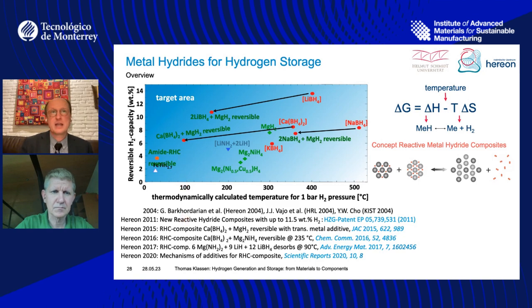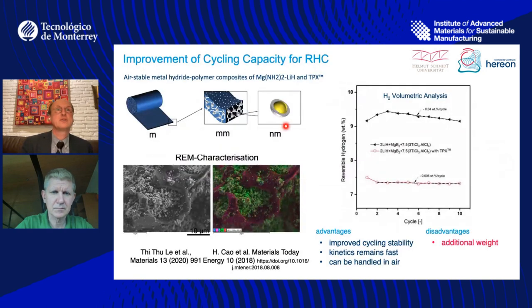And this is why in the next step, we try to bring the reactants closer together by encapsulating. And that helps us to promote the reaction. However, temperature is still very sluggish at 90-95 degrees C.